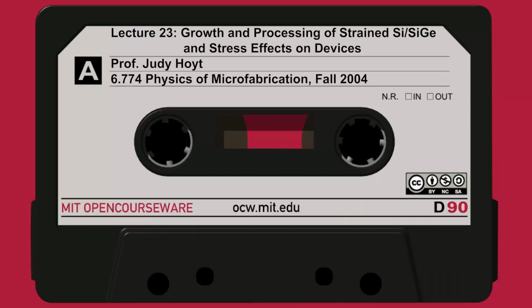There are other processes during fabrication that Intel is using now, where they actually dig out the source and drains. They cut them out with etching, and they fill them back up with silicon germanium, which compresses the channel, which helps the hole mobility. So people are doing things like that. You can actually stress the device. People put a layer of high-stress nitride on top of the device and try to induce stress by applying films that are high-stress.